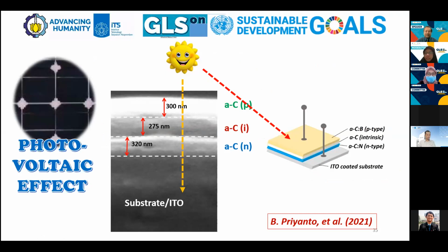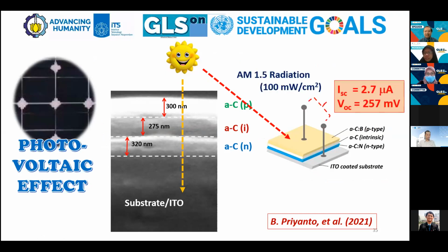And after irradiation using the AM 1.5, the short circuit current and open circuit voltage can be detected. It is considered to be too small. However, this at least shows the photovoltaic effect can be detected from the device. This is a PIN junction made of all amorphous carbon film. This is very rarely reported before.